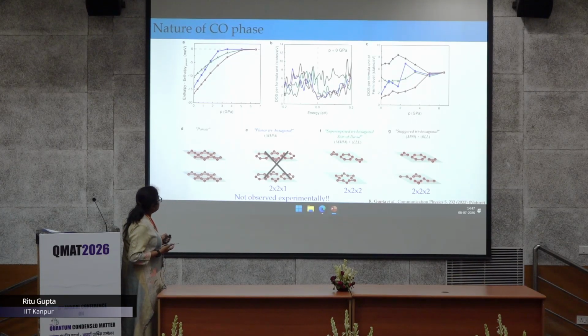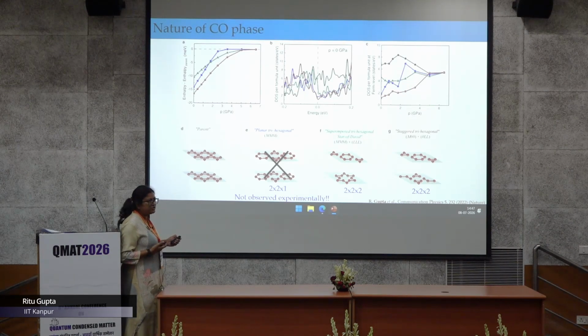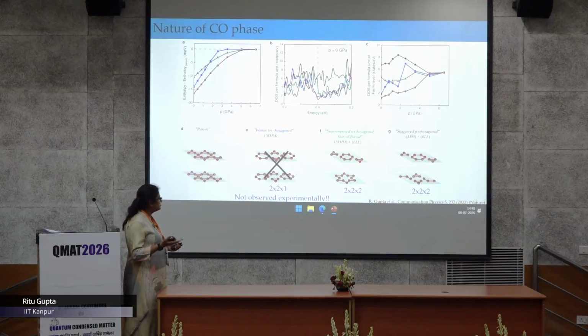But if we look at the density of states per formula unit, this Star of David phase has higher density of states, that means higher Tc, and the staggered trihexagonal phase has lower density of states, showing the lower Tc. That means this is the phase which is most probable in region 1 where we have higher Tc, and the staggered trihexagonal should be in region 2. So we have two distinct charge order phases in region 1 and region 2.